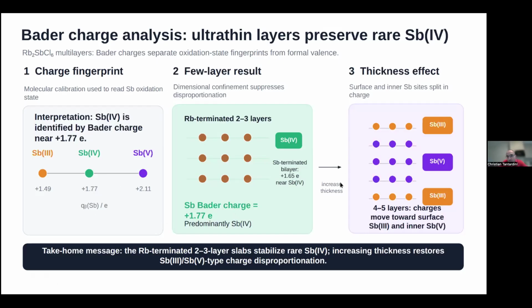When we increase the thickness, we saw that from 4, 5 layers there is a disproportionation. So we got a kind of trend that stabilizes antimony 4 at 2, 3 layers of rubidium-terminated, and with increasing thickness it restores the disproportionation that is seen in the bulk.